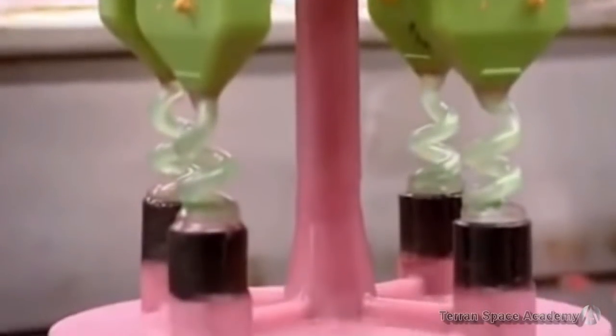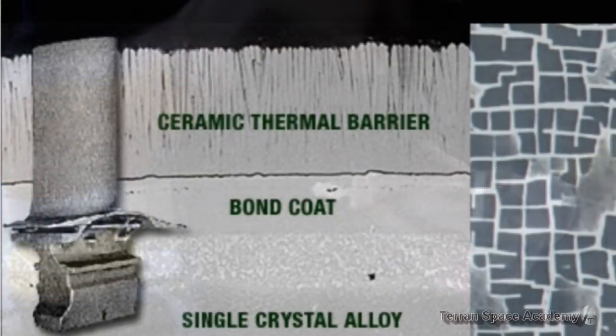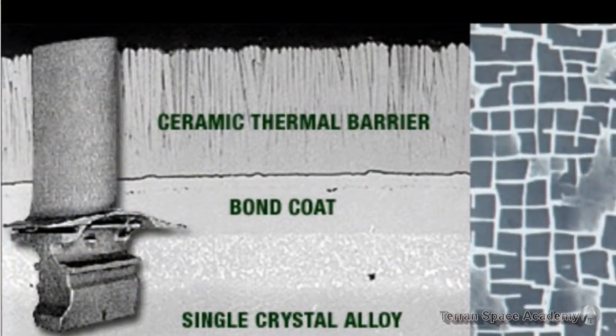The ceramic mold is then heated in a furnace, and molten alloy is poured in through a helical structure to spin the molten alloy for even distribution. The mold is filled and the alloy hardens. The ceramic mold is dissolved in a caustic alkali solution. Holes for the cooling air are precisely drilled out with electrical discharge machining. Then electron beam physical vapor deposition is used to apply the insulating ceramic coating over the single crystal alloy blade.